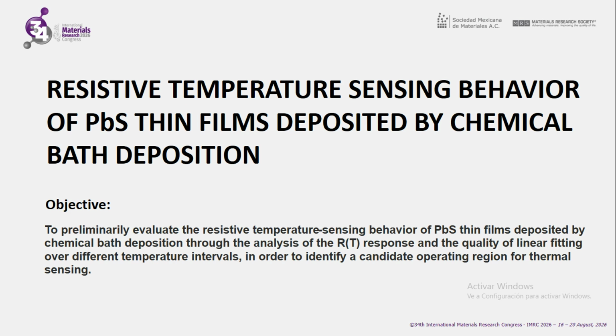Resistive temperature sensing behavior of PbS thin films deposited by chemical bath deposition. Objective: to preliminarily evaluate the resistance temperature sensor behavior of PbS thin film deposited by chemical bath deposition through the analysis of the RT response and the quality of linear fitting over different temperature intervals, in order to identify a candidate operating region for thermal sensing.